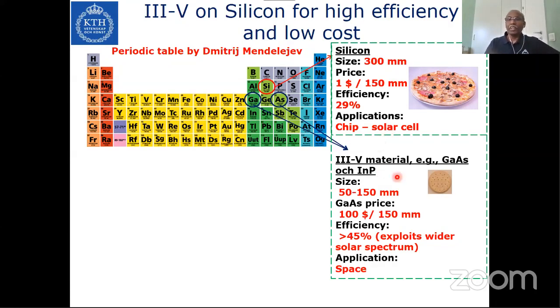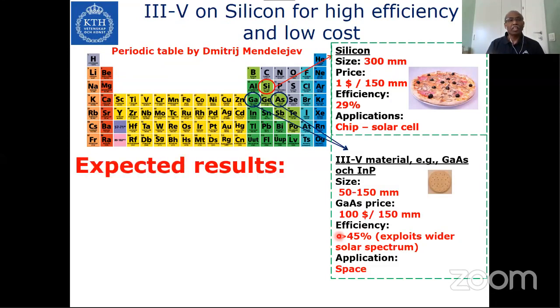But the III-V materials, the size of the wafer is like a biscuit, and the size is 50 to 150 millimeter, and the cost is $100 per 150 millimeter. You see, this is a very huge cost, okay? But the efficiency you can obtain is 45%. So why not you combine these two? So if you combine, expected results are two birds in one bullet.